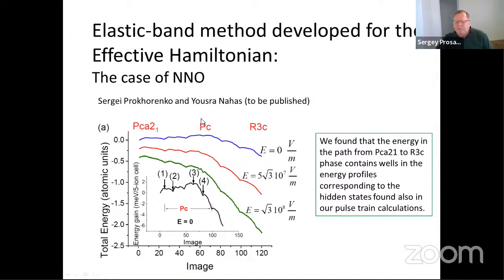The intermediate states have PC symmetry. And you see that in this path, this is energy versus the image number in the sequence from Pca21 to R3c phase. So we see that there are some small wells in the path from one phase to the other phase. And these hidden states are exactly the same, at least the polarization is the same, as those states we found during the train of the electric pulses.